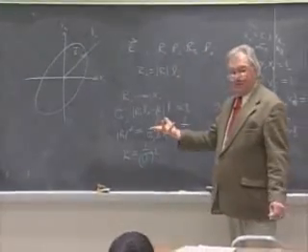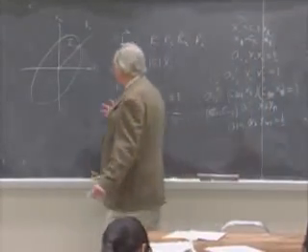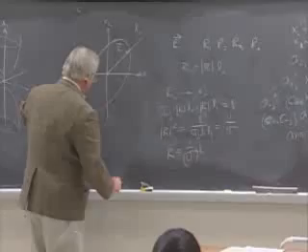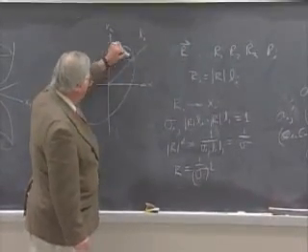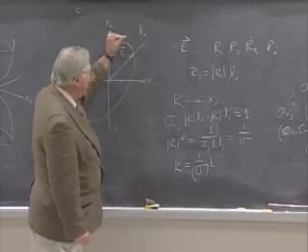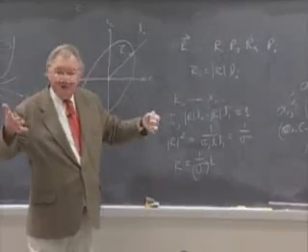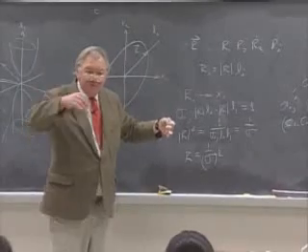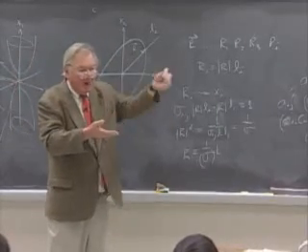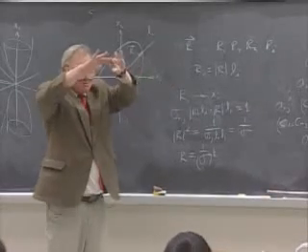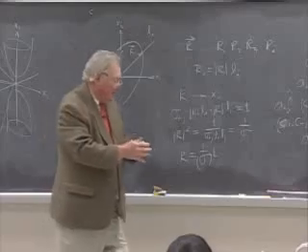There is an enormous implication here. If the quadratic form is an ellipsoid, the value of the property as we go around in different directions in the crystal is going to be a smooth, uniformly varying function. There are going to be no lobes sticking out, no dimples, no lumps. It's not very interesting; it's going to change in a uniform way.